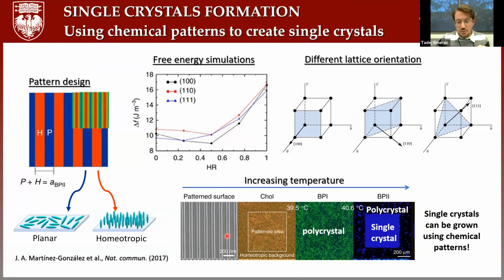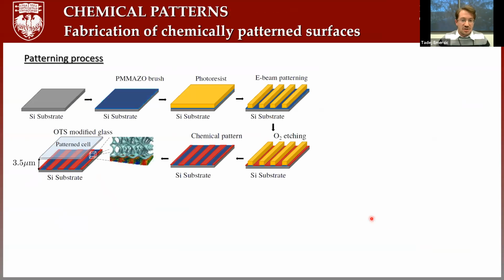So on the pattern region, we inject the blue phase at the low temperature. At the low temperature, this liquid crystal or blue phase is actually chiral nematic, right? So cholesteric phase. And then we keep increasing the temperature. As I mentioned at the beginning, the system at some certain temperature is going to go into the blue phase, generally into polydomains, but because we have patterns here, on the region where the patterns are, single crystals form. So they showed this. And what these patterns actually are.